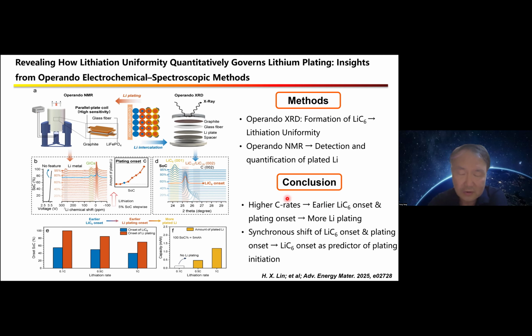If you charge at a high rate, more LiC6 will be formed, leading to the formation of lithium dendrite. So we believe that LiC6 could be an indicator of lithium dendrite formation or lithium plating, because if the graphite is fully lithiated, it causes lithium plating. Earlier LiC6 onset and earlier lithium plating onset cause more plated lithium.